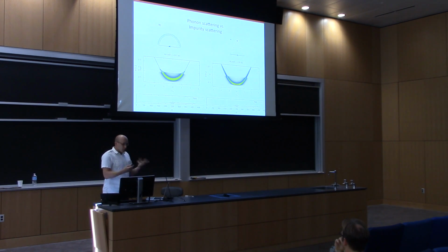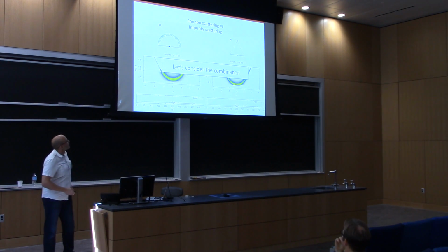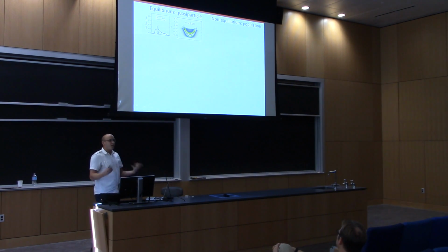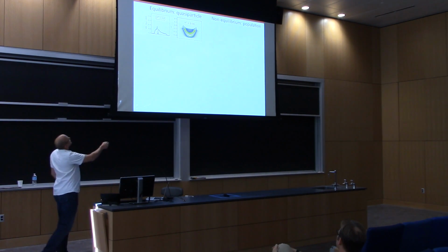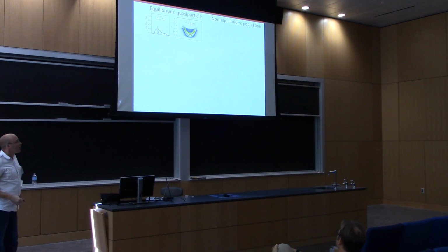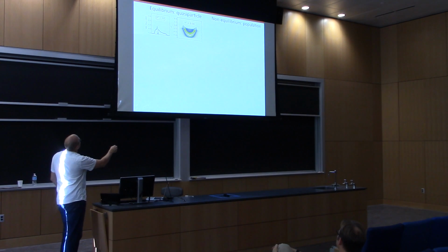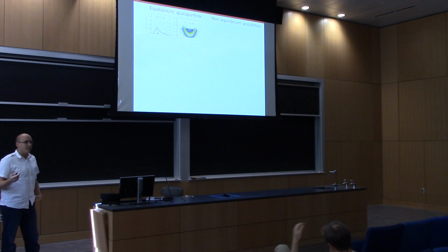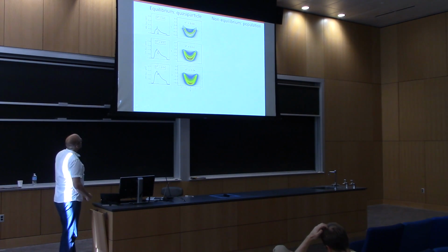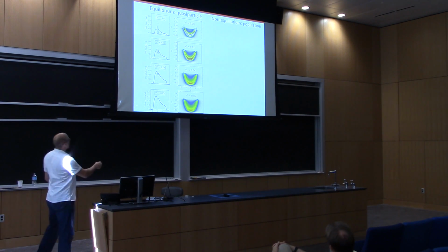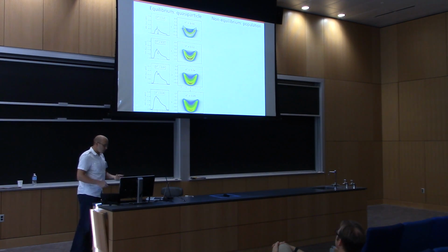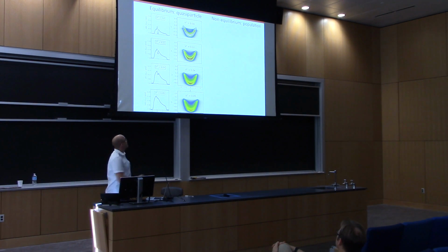So, what was going on? Let's see what happens when we take both. What I can do is the normal sorts of things, and I can calculate what my self-energy should be and what my spectrum should look like. So this is where I've taken just electron-phonon scattering, no impurities. This is what my spectrum looks like. I've got a nice kink. I've got the self-energy, which has this phonon window. And now I start adding impurity scattering. And sure enough, my spectrum gets nice and broad. My self-energy loses this gap in the middle because it doesn't exist anymore. It's being filled up by all this electron impurity scattering because of Matthiessen's rule, right? Scattering rates should add.